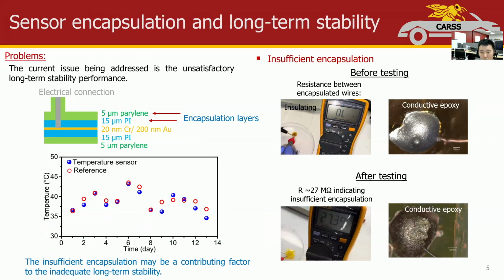The current issue being addressed is the unsatisfactory long-term stability of the temperature sensor. When immersed in PBS, the testing data will be poor over time. Limited long-term stability is likely due to insufficient sensor encapsulation. As you can see here, the color of the conductive epoxy changed significantly, and the protective thin film lost its insulation after long period test. This observation suggests that the encapsulation fails to protect the sensor effectively from water moisture.